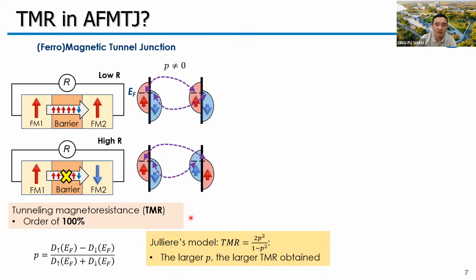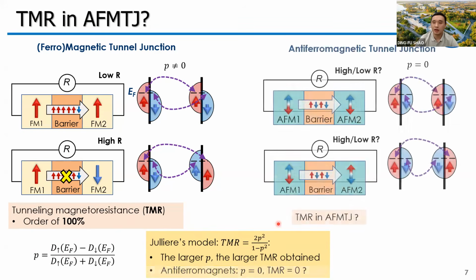This picture can be understood by this empirical model where P is the spin polarization of the current within each electrode. P is usually defined according to the density of states. Obviously, the larger the P, the larger the TMR we should expect. And for antiferromagnets, because we usually have the spin degenerate density of states, P is obviously 0 according to this definition. So according to this model, it seems very difficult to realize TMR in antiferromagnetic tunnel junctions.